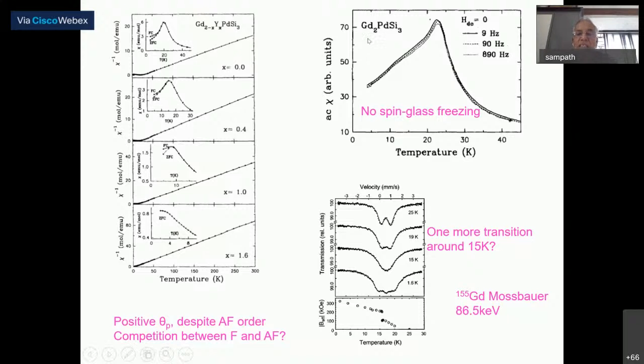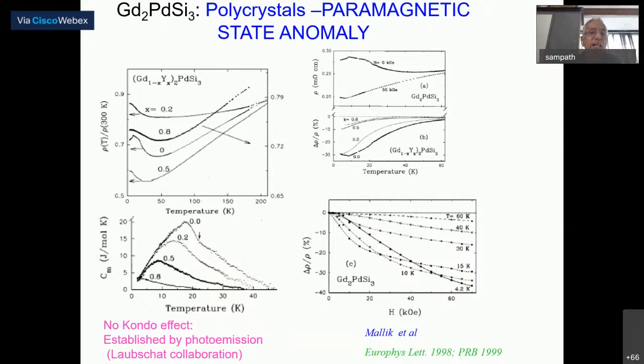And when we measured the AC susceptibility, look for spin glass. There is no evidence for spin glass in this material. This raises the question: what is happening to the competition between these? Now we look at electrical transport. This is probably one of the most important figures.